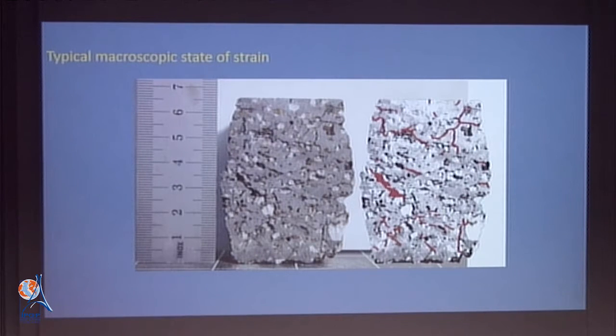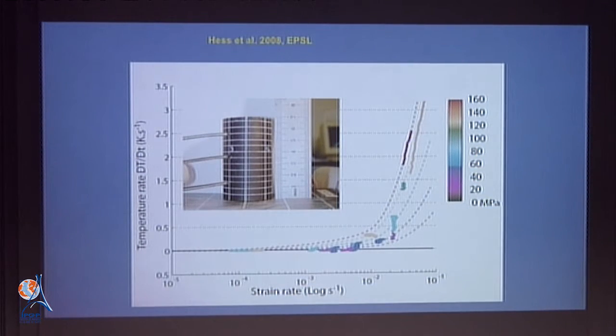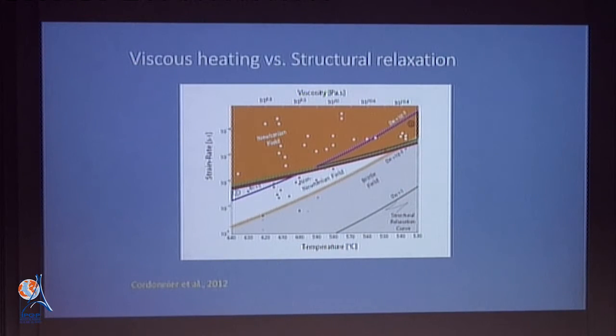You can probably immediately now get a feeling for whether or not you think that this is a representative through-going deformation of the sample, which is, in this case, multi-phase. And we can measure the very, very subtle temperature increases due to viscous heating in these materials in situ during deformation, basically under the conditions of deformation in the Earth. The same rates, the same temperatures, and because we're dealing with volcanic domes and flows, which are basically at the surface of the Earth, under the same pressure. So we're as close as you can possibly imagine to getting to the actual deformation environment in nature.